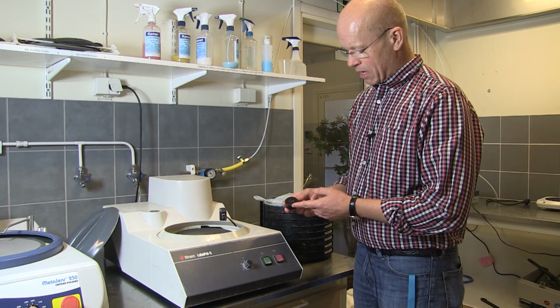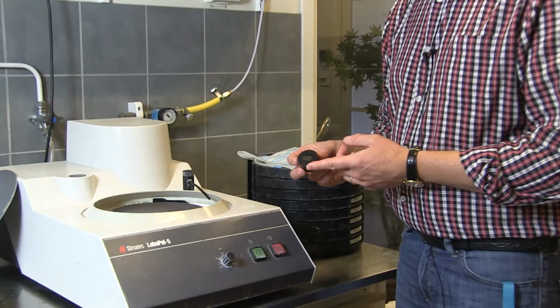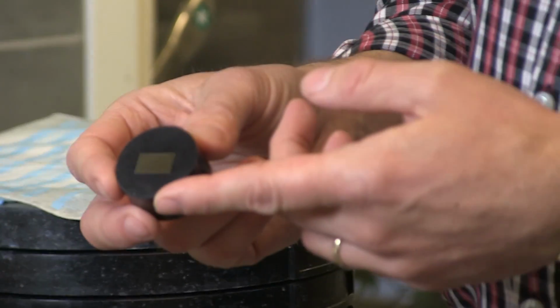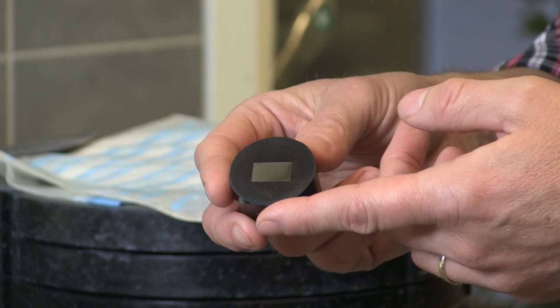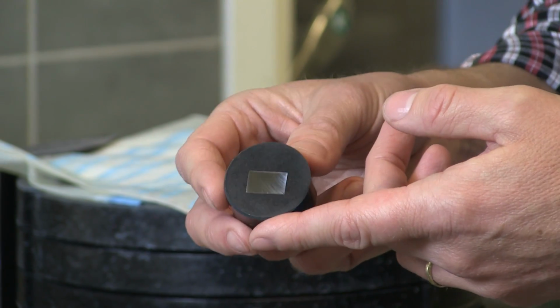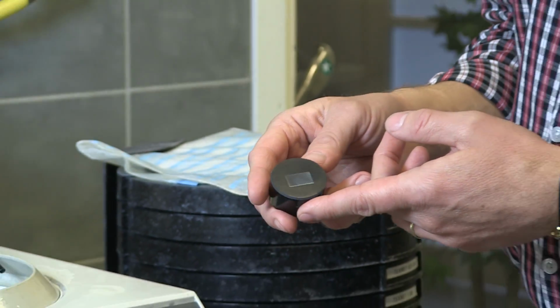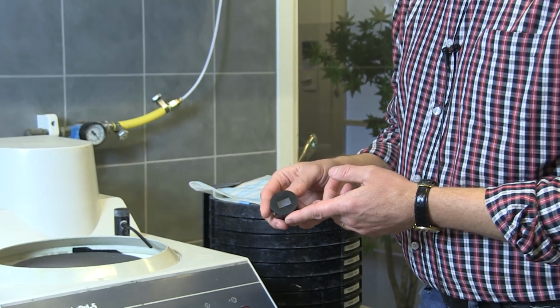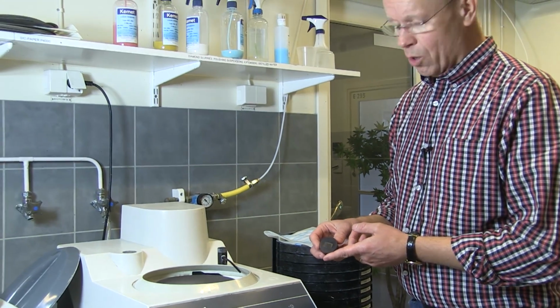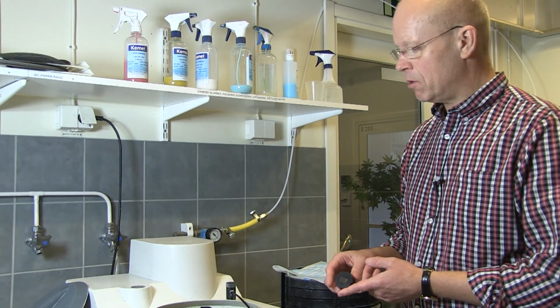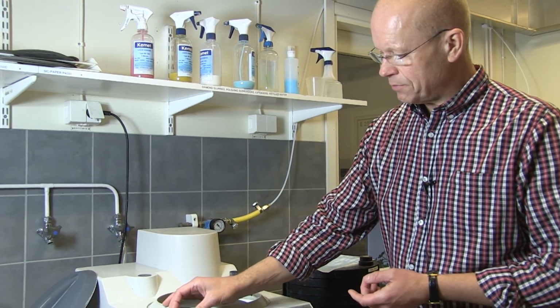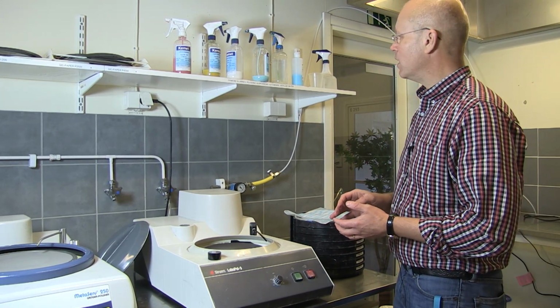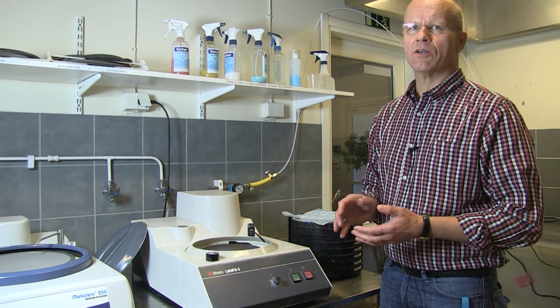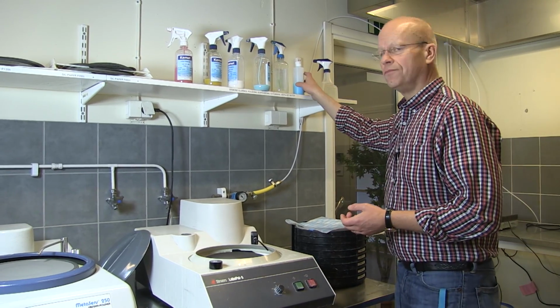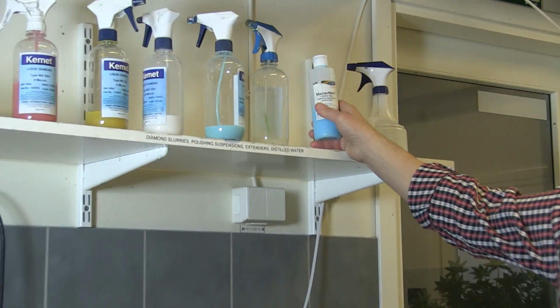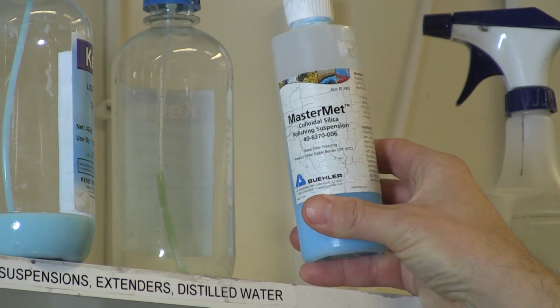So after cleaning the sample after the 3 micron step, it's time to move on to final polishing. In the description I gave you, I also mentioned 1 micron diamond as a possible step, but as a matter of fact, this final polishing is very effective. So usually on a low carbon steel, it will work to go directly from 3 micron to final polishing. Final polishing is, instead of diamonds, made with a suspension of silicon dioxide, which we also store up on the shelf here.